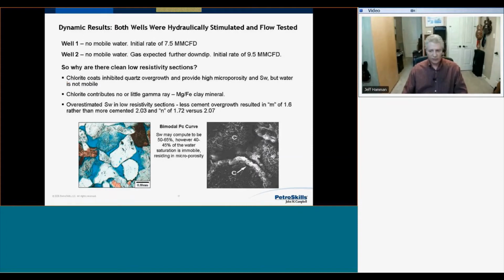And the last point, sorry about the laser pointer running around. The last point was that we overestimated water saturation in the low resistivity zones by using the same Archie parameters in the cemented and the uncemented. So with less cement overgrowth, less quartz overgrowths, we would see an M of 1.6, and in the more cemented intervals, a 2.03. So if we assumed, as we often do with the lack of information, that M would be equal to 2, we're not too far off in the cemented region, but we overestimated the formation factor in the less cemented or the clay-coated region.